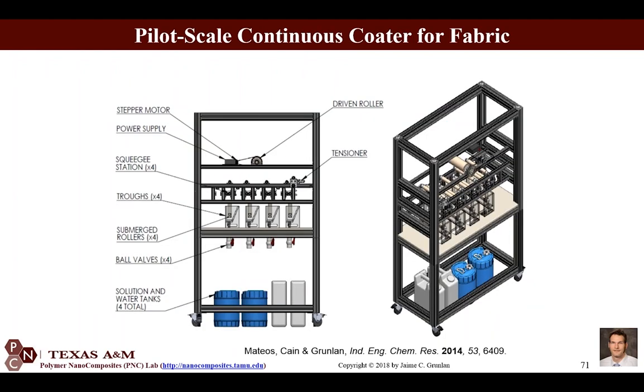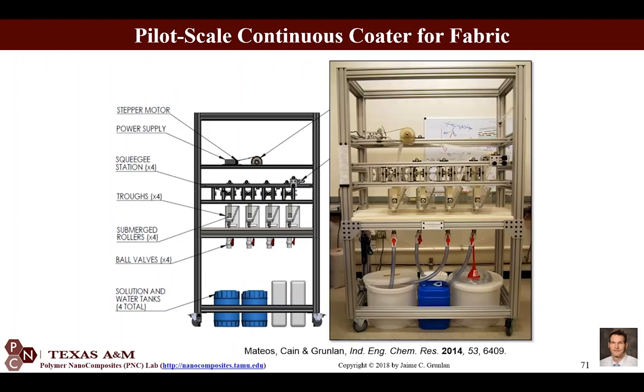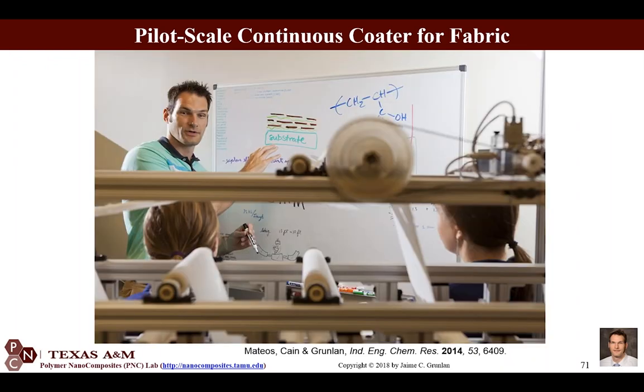So I'll just finish up by showing, even in my own lab, we built a little pilot coater. This is basically what you would call pad dry processing equipment. Film goes in and out of liquid deposition baths. I know that there are companies, and even Paula Hammond's own research group created a technology of spray coating layer by layer assembly. So there's 5 or 6 different water coating methods that you can use, some very traditional ones, to deposit roll to roll layer by layer assembly.